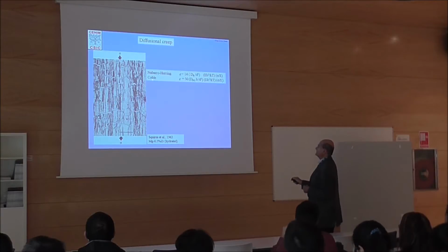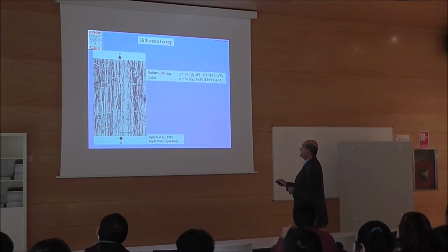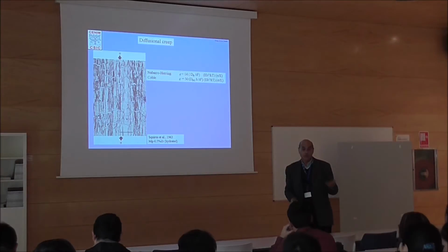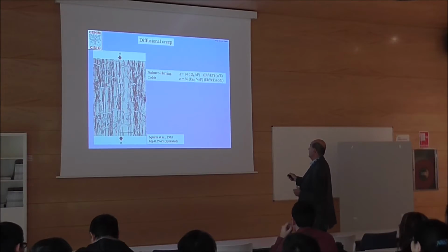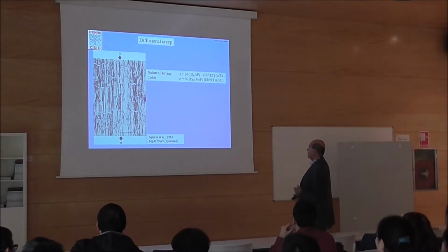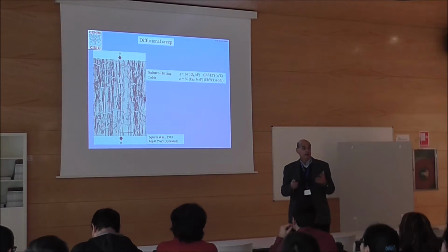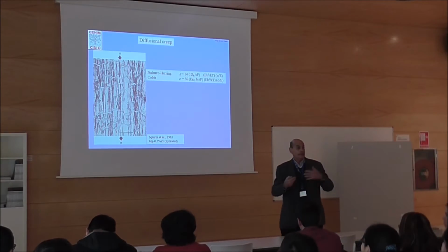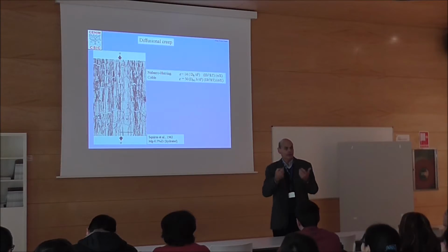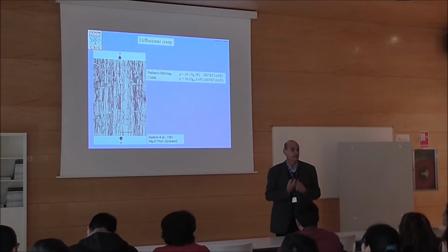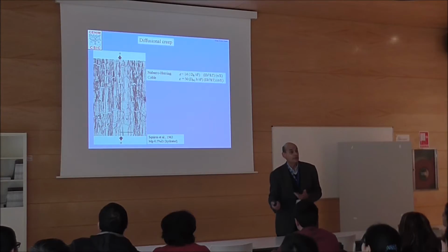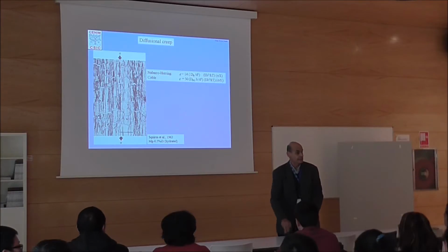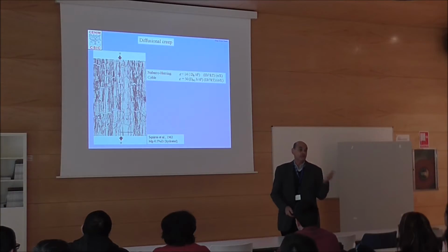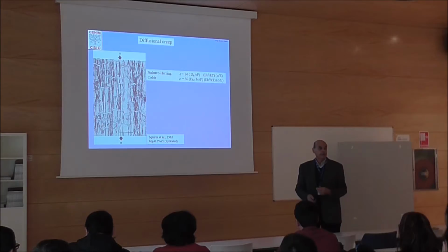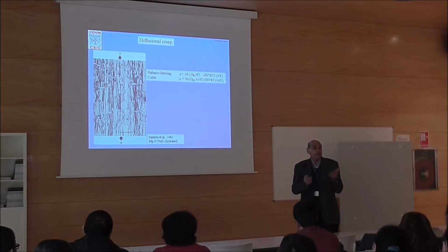Coble in 1963 said, okay, well, it goes through the lattice, but it could go also through the grain boundaries. And we have the same effect, and that's why we have diffusivity along the grain boundaries. So as I mentioned, it's a wonderful theory, but this is also philosophy. You have to accept my critics. It doesn't exist, because grain boundary sliding is more important than this. I have never written this in a publication, but I have demonstrated that probably in most cases it doesn't exist. But the theory is very nice.